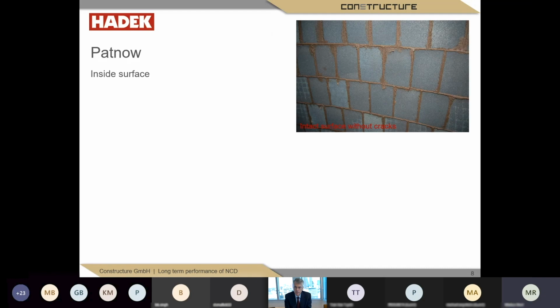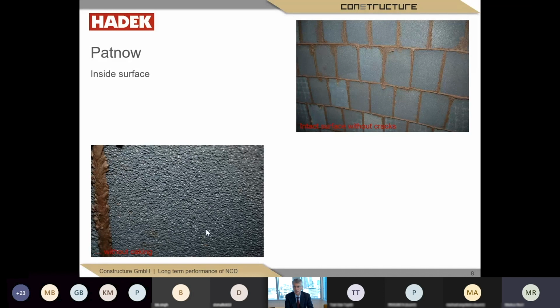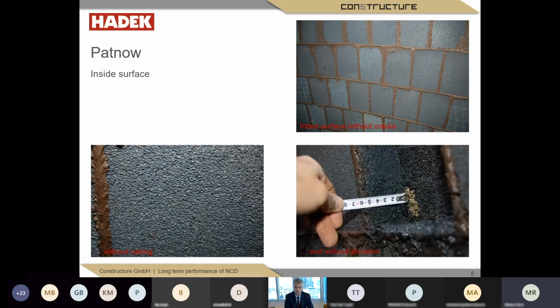We got photographs from the inside surface, and here you can see that the Penguard individual blocks are intact without cracks. You can see the adhesive at the edges of each block, which is still there, and it was flexible. You can see a detail of a block surface with the pores, and there we have no dust deposits. And if you compare it with the joint on the left hand, you can easily see that there's no wear-off, no abrasion of the internal surface.